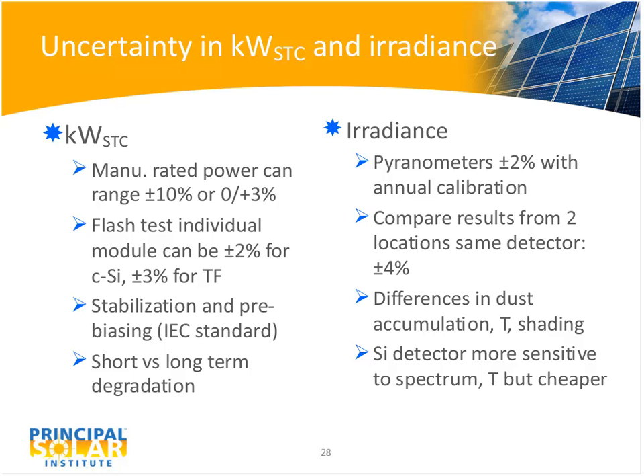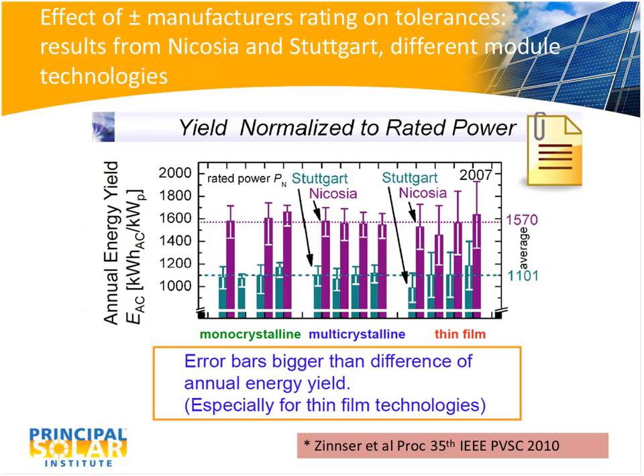And if they use a different type of detector, like a silicon detector, which has more sensitivity to the sky spectrum and temperature, but they're cheaper, you can now increase these uncertainties even more. So you start looking at these numbers and you realize that the best you can do would be maybe 5% between locations, and without much effort at all, you could be looking at plus or minus 10%. And that's what a number of people have concluded about comparing results from different sites.